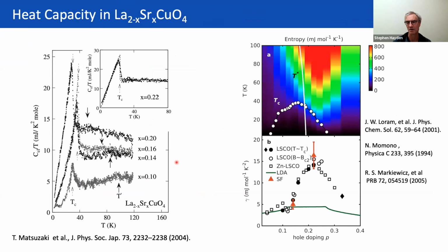The previous plot I just showed actually involved doping a system with neodymium and europium. So here's some data on the pure LSCO, and here's some actual raw data from a Japanese group showing the specific heat, and you can see here in the normal state, as we change the doping, going through about 0.19, the P star composition, the linear part of the specific heat increases.